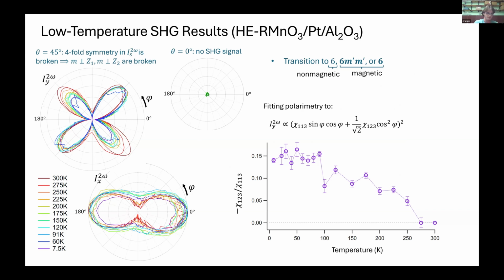And we are also checking a normal incidence to rule out other possible transitions. We have the X polarized intensity as a function of temperature too. This unfortunately doesn't tell us much because the spreading out of the polarimetry is not exclusive to the phase transition. And we can also plot our new tensor component that emerges below the phase transition as a function of temperature, and we see it saturate.